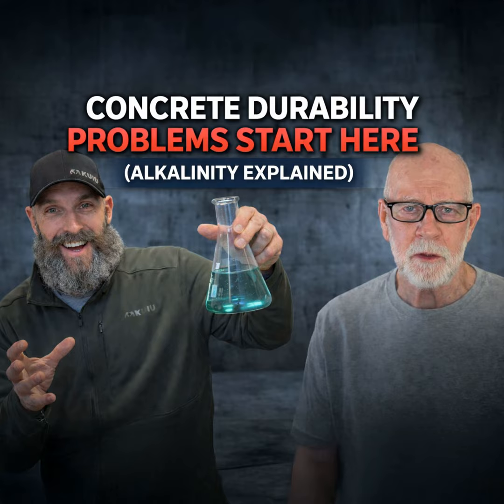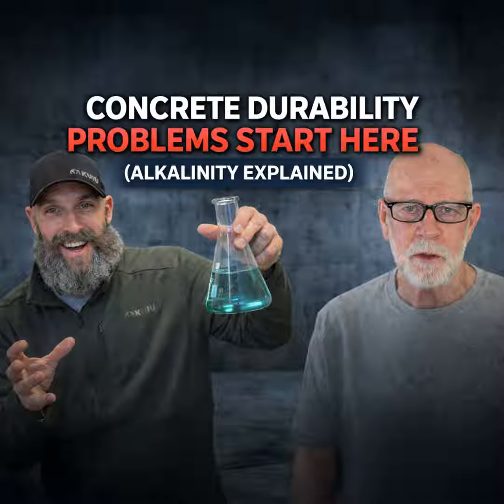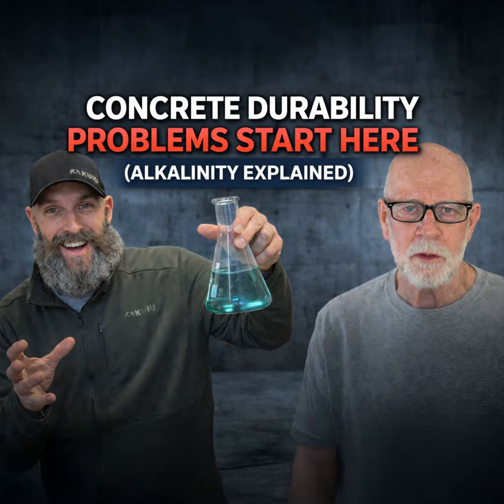That's beyond its capability. Now, when you have a lower RH, that also equates to a slower evaporation rate. So things like the calcium chloride test, because it's fixed at 60 to 72 hours, there's only so much moisture it can capture in that kind of a climate versus an open system where it can readily capture moisture and will give you an accurate reading, especially now with the cement kiln dust in there. And now with the changes in concrete, that's no longer a viable way of measuring moisture content. RH and calcium chloride are not viable.